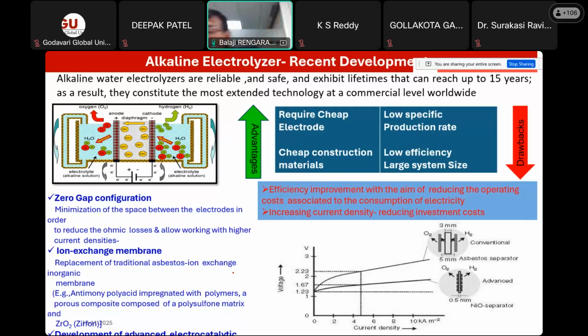So in this step also, when you try to reduce the inter-electrode distance as close as possible, obviously you have to avoid short circuiting. So you have to introduce some separator which will do the gas separation, because each electrode will produce the respective gases, hydrogen and oxygen. You have to separate this hydrogen and oxygen, otherwise again the explosion will happen. So you have to introduce some separator material which will separate the electrodes and the gases.